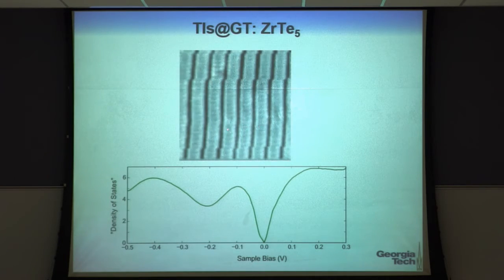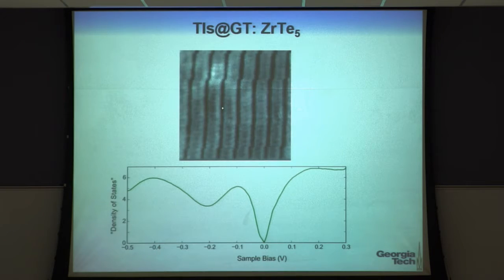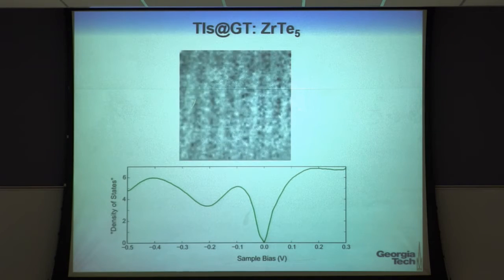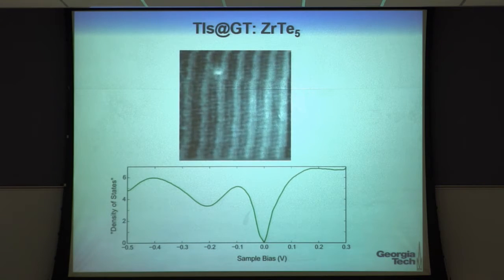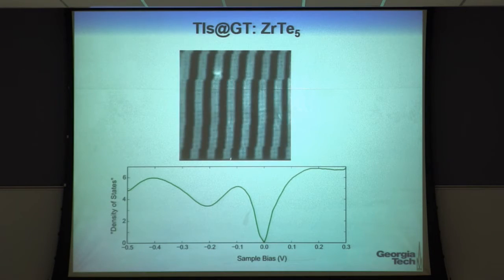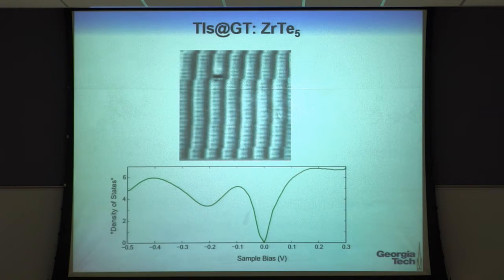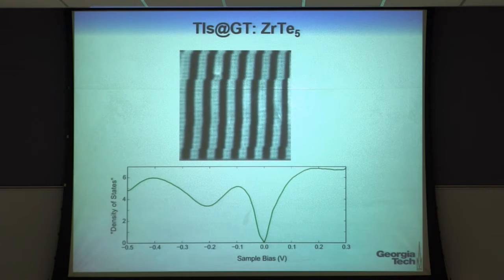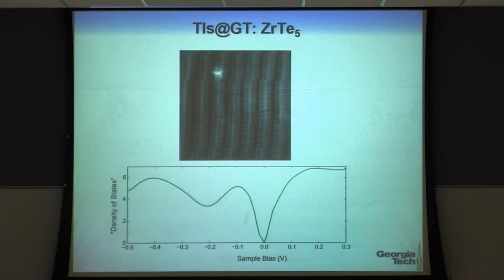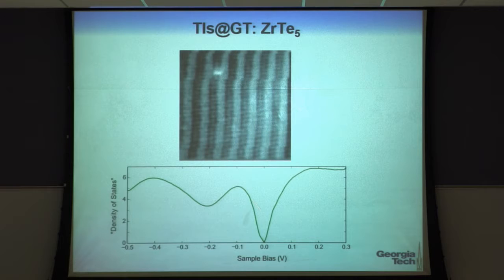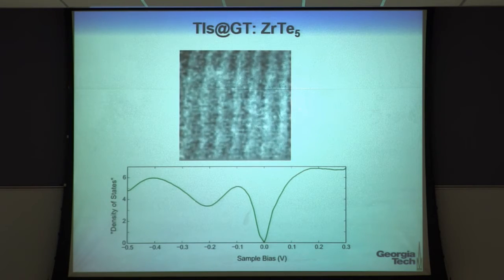Okay? And so what D is trying to figure out these days is exactly where are the filled states, where are the empty states. It matters because then we can compare to a band structure calculation and not only look for the energies, but is this a tellurium in the zigzag range, or is this a tellurium in the dimer rows? And those determine the symmetries of those states when we compare to a band structure calculation, for instance. And we're also trying to determine whether there are states living within this band gap.